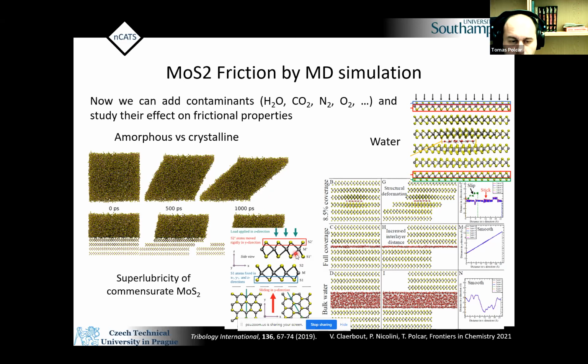superlubricity of commensurate molybdenum disulfide, where we showed that we can get extremely low friction even for commensurate molybdenum disulfide without rotation, only when the sliding direction is out of the 0 or 60 degrees of molybdenum disulfide, as you can see here. Or we can add some water in between, which again is a little bit difficult because of force fields, but we can observe the effect, for example, of these contaminants on molybdenum disulfide.